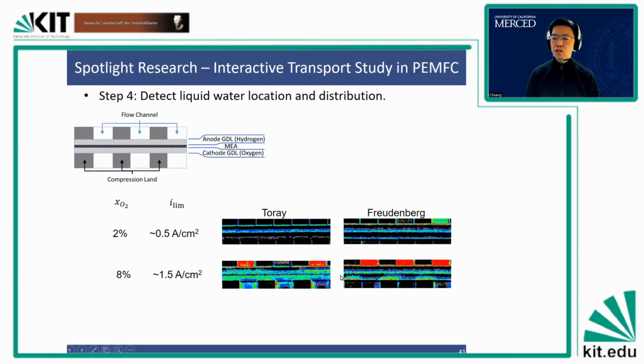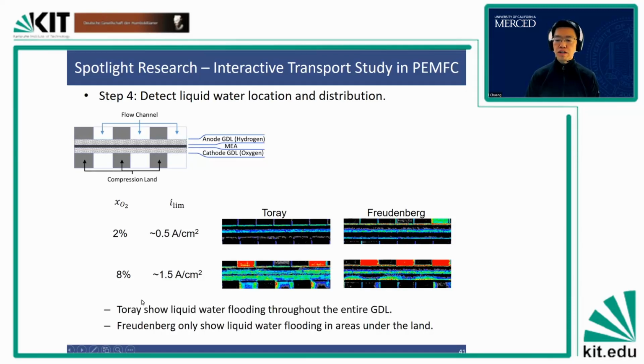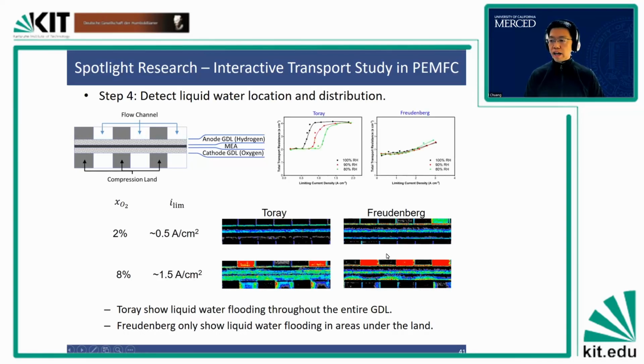And this actually corresponds to the compression land and the channel. So oxygen is fed in the channel, so there is no problem for oxygen to diffuse into this catalyst layer. But for the Toray material, you can see that this layer is all wet, and this water exists within the entire layer. For Freudenberg, the distribution of water is very different. So it shows that Toray has flooding on the cathode diffusion media throughout, but Freudenberg shows only a limited area. And this observation agrees perfectly with our characterization tool through the transport study.